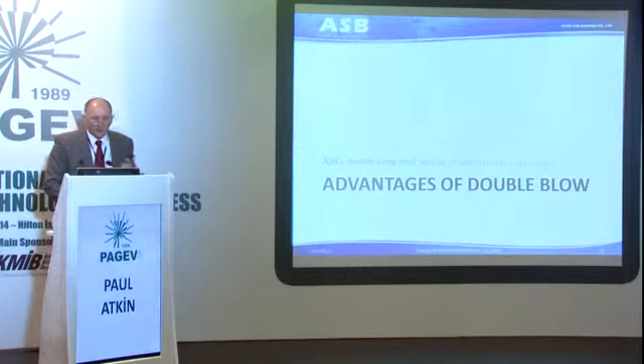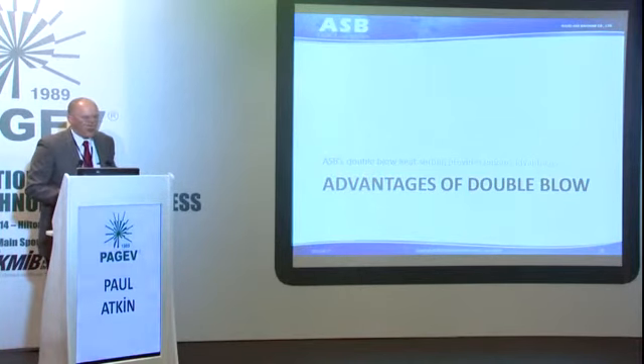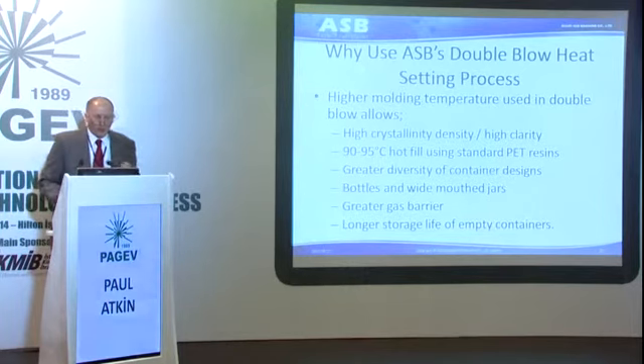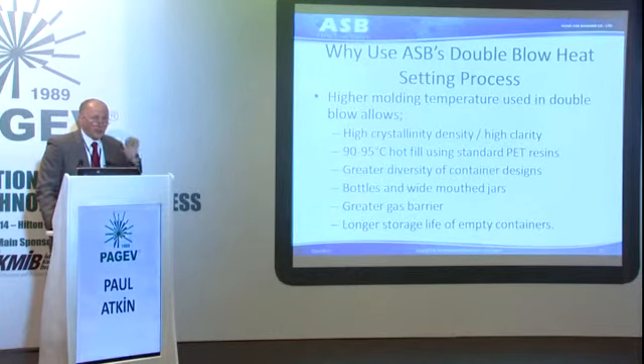So I mentioned that our process is called double blow, so I just want to explain the advantages of that and how it's different to other forms of blow molding. In double blow, we use a 2-step blowing system. This is not the same as 2-stage PET stretch blow molding. What we're doing here is blowing once and blowing a second time. And by doing that at high temperature, it allows us to get high crystallinity in the PET and high density, which allows 90 to 95 degrees C heat resistance using standard PET resins. And that's one of the key points about this. We don't need to use anything special in terms of material. This allows us also greater diversity of container designs, bottles and wide-mouth jars, and it also allows a longer storage life for the container, both before filling and after filling.